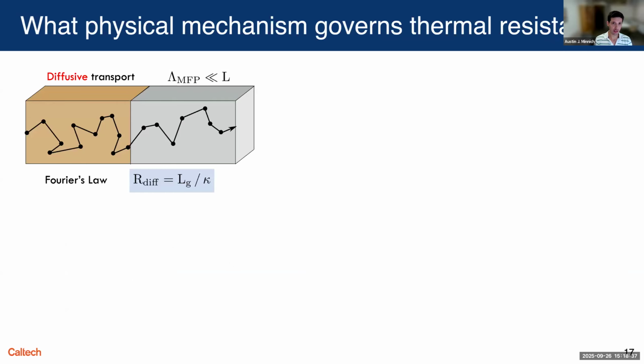All right, so how to reconcile that? The key insight is that at cryogenic conditions, the heat conduction mechanisms are different than they are at room temperature. Typically we describe heat conduction with the equivalent of Ohm's law, where we have diffusion of heat carried by lattice vibrations. And as long as the mean free path of those lattice vibrations is small enough compared to the relevant lengths, then that's when we get the equation for the diffusion resistance.